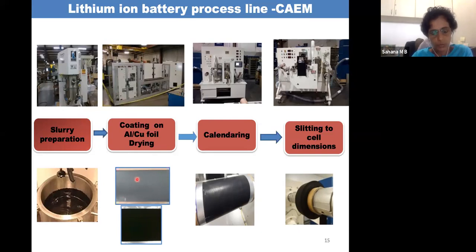Now since we have used liquid in the slurry preparation, when we dry it off, it leaves some pores. Depending upon how much of the solvent we have used, it will leave the pores. So we need pores, but we need to control the amount of pores in this film, so we compress it and reduce the porosity. That process is called calendering. Then once we calender that, we need to cut these electrodes to the width we require. We call that slitting of the electrode.